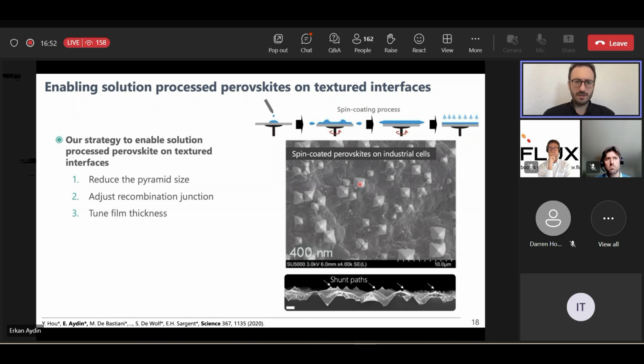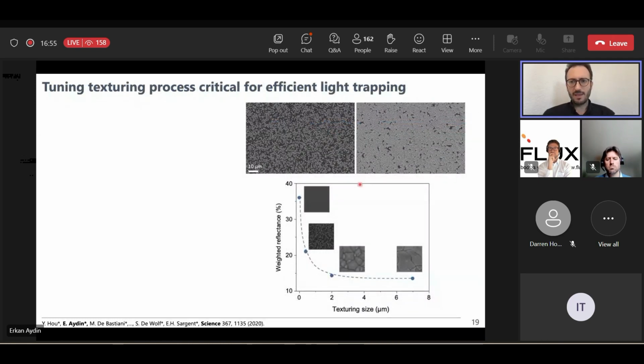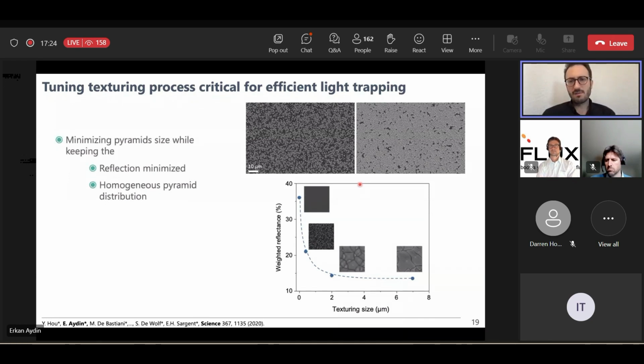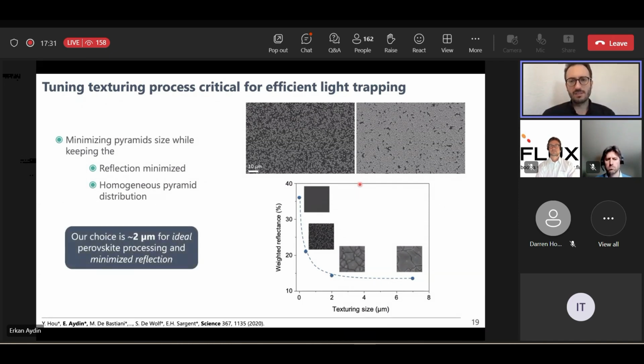First, we studied how to reduce the pyramid size, because typically the pyramid size in the market was around the 5 micron, 6 micron level. The idea was reducing the pyramid size, still enabling a continuous, homogeneous distribution on the crystalline silicon surface, and still minimizing the reflection with a meaningful pyramid size. For this, we did several optimizations of the etching process, and we found that actually 2 micrometers and less is the ideal size for perovskite-silicon tandem cells.